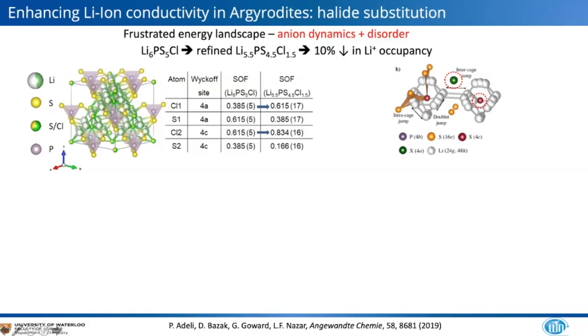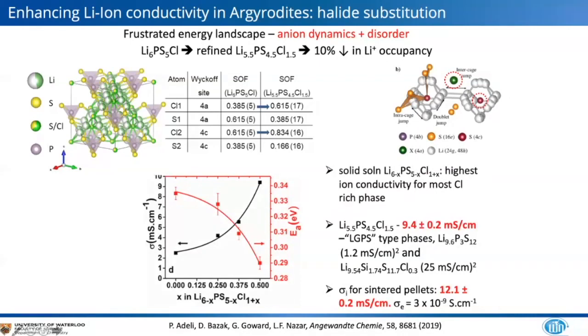And you can see that the chlorine distributes on both sites, the 4a and the 4c. So we're not really increasing the anion disorder, we're simply putting more halide into the lattice. And so the activation energy drops as we add the halide, and the conductivity dramatically increases. So we are at a conductivity of about 9.4 for the highest chlorine concentration that we can achieve, which is the chlorine 1.5 phase, and that goes up to about 12 millisiemens for sintered pellets.